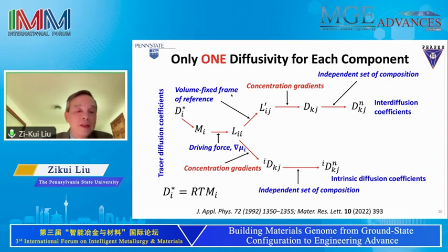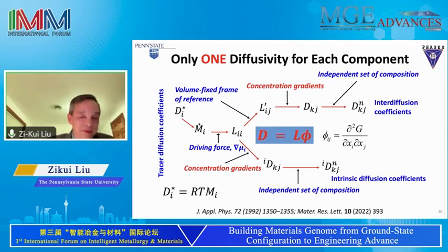Okay, so what does it mean? That means from one parameter we get a vector. This is because of thermodynamics. It's a second derivative of energy. Times that parameter gives you all the other diffusion matrix elements. They are not independent at all. But they have different values because it is one value times this thermodynamic factor. And of course, the thermodynamic factor is different for different elements. So that's why I get the matrix. Okay? So that's very important. What does it mean? That means some equations we have today are inaccurate. Or actually, I would say they are wrong.